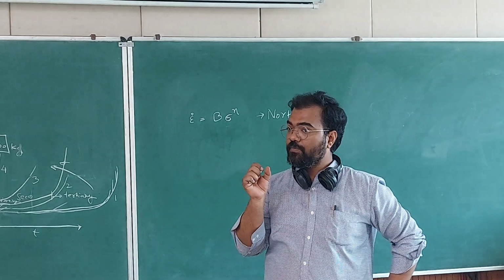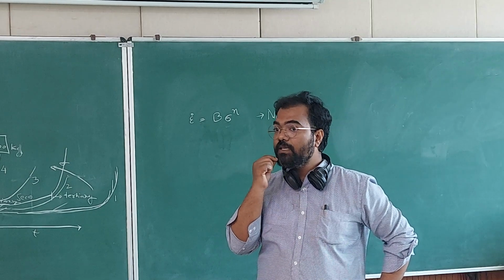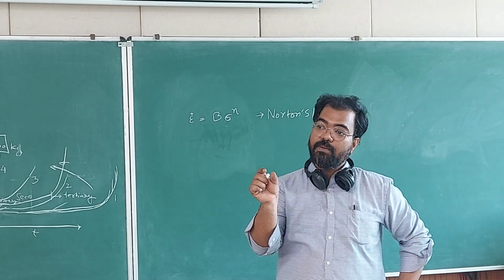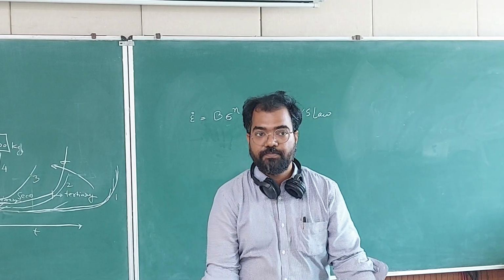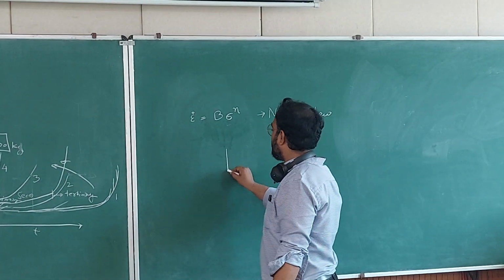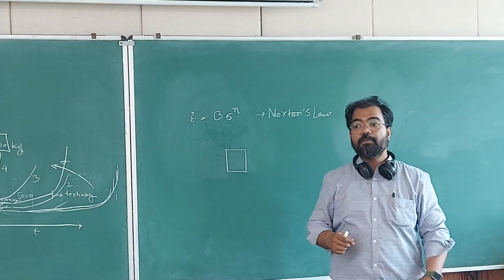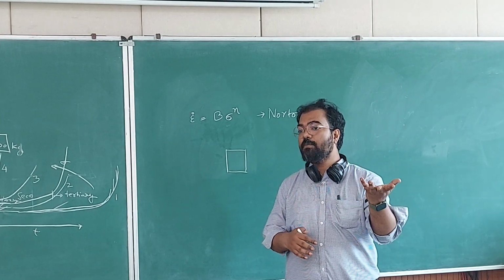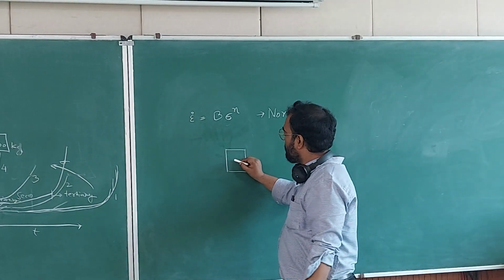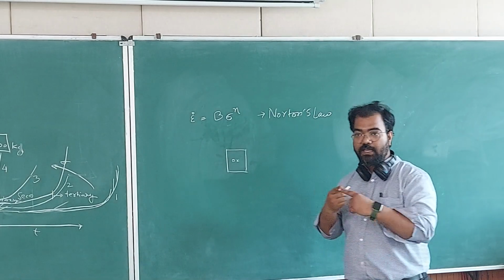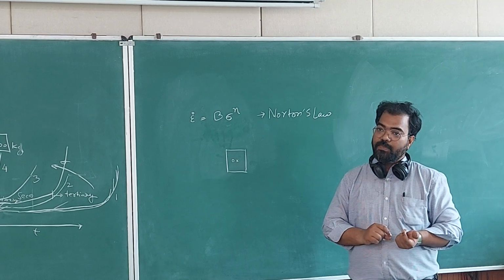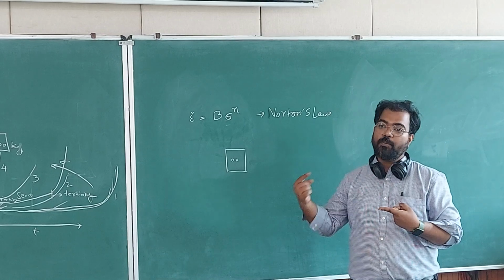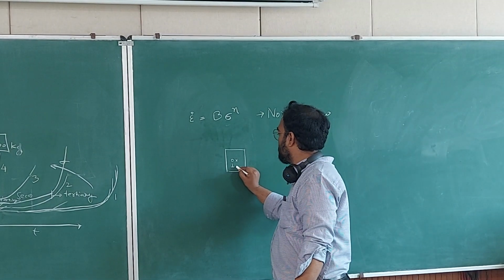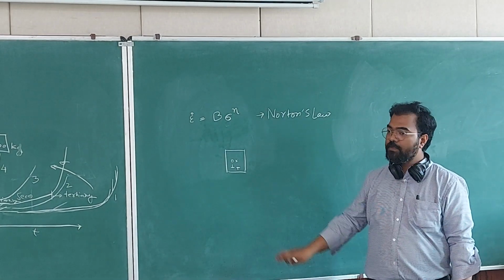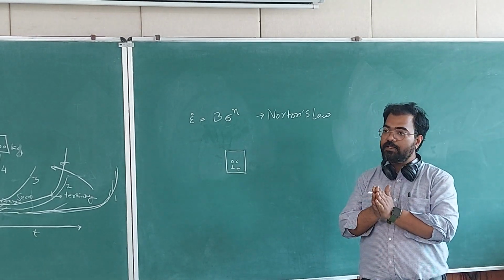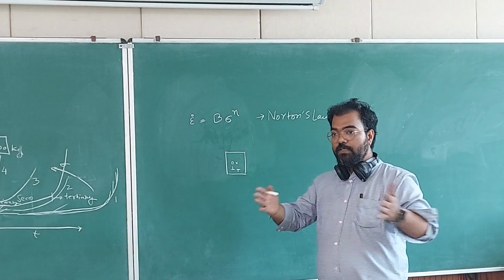So then what other thing can happen is that you can have stress induced diffusion. Okay, and for diffusion you need vacancy and you also need dislocations. So one concept is that vacancy interstitial pairs are created in the system. Okay, this is a weird concept. So out of nothing something happens. In one of the thesis proposals this question was asked, that if you have a perfect crystal, then how will the dislocations come up? So similar to that, if you want to create a vacancy, you will also have to create an interstitial so that it can nullify. If you create a positive charge, you have to have a negative charge. If you have a dislocation, you have to have another dislocation in the opposite direction, which can nullify. So if you have a dislocation like this, you will have to have a dislocation like that. Okay? So when they will join together, then there will be a perfect crystal. So from a perfect crystal, 2 dislocations can come up. This is the homogeneous nucleation of dislocation.